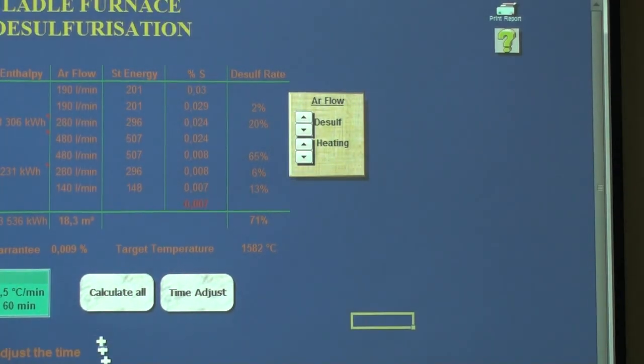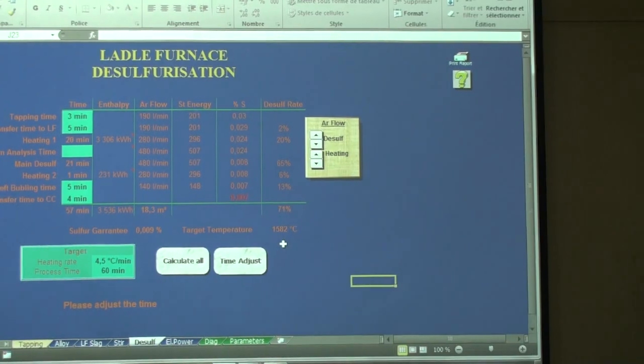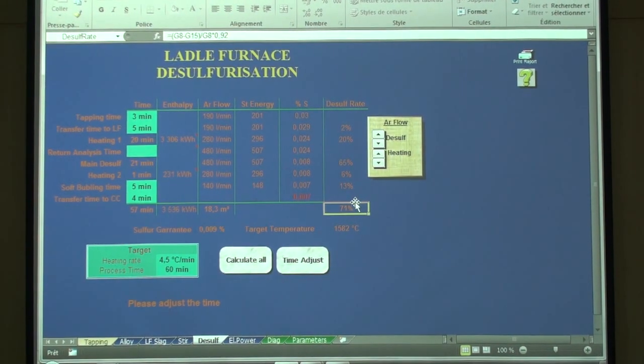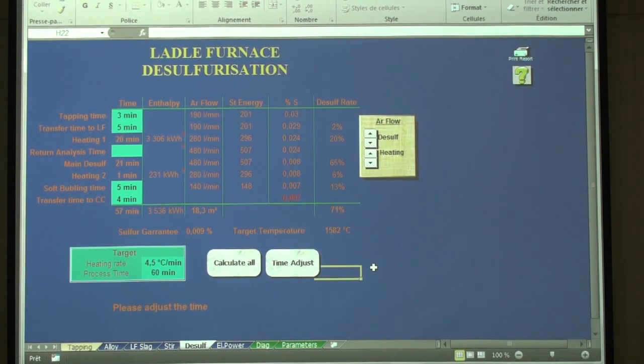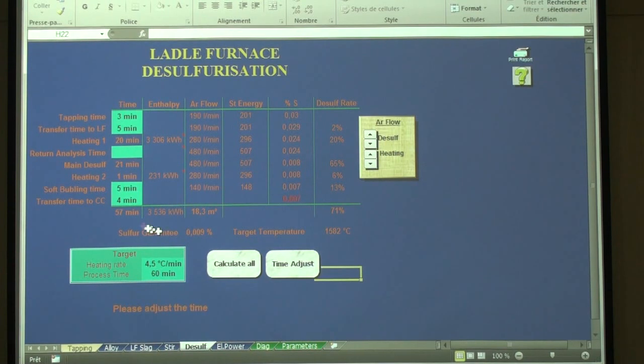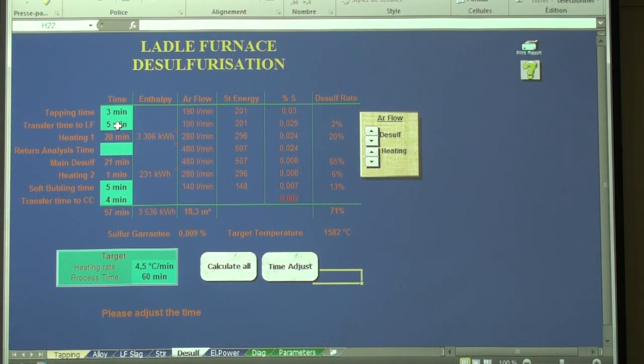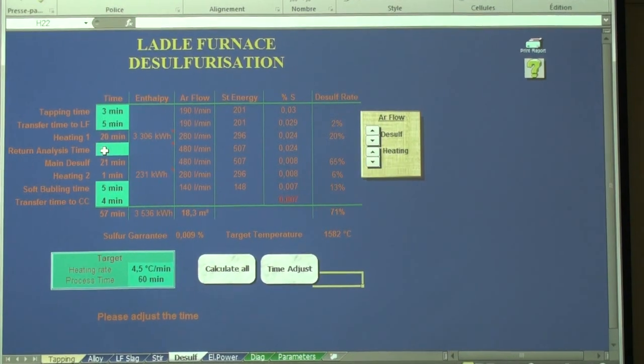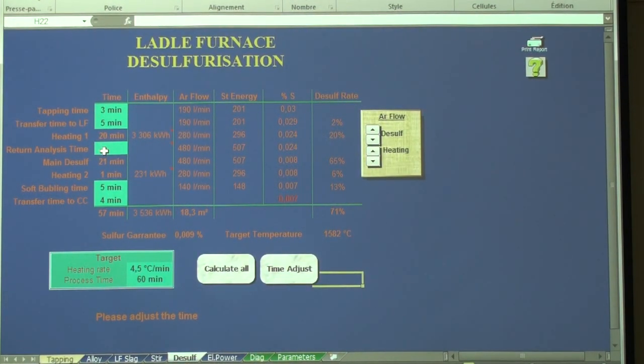Then we come to the desulfurization. Because for desulfurization, the desulfurization rate and final sulfur, the time is very important. So we have to consider all the time where the steel is in the ladle. Tapping time, transfer to ladle furnace, first phase of heating, then some power off, for example, waiting for analysis, then main desulfurization. So it's combined here because I assume it's power off. And this is the second heating, and then soft bubbling time for the inclusion decantation, and then the transfer to CCM.